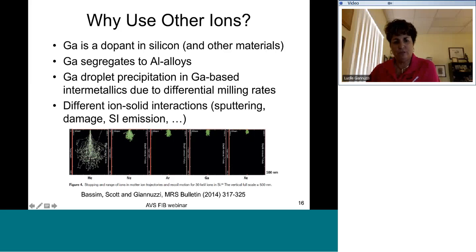Helium has a very small spread at the surface, but then travels microns length into a sample. Whereas these other ions that exhibit so-called sputtering and heavy ion effects will be stopped only a few tens of nanometers within the surface. So it really depends on what you want to do, how you want to do it, what effects you want to get for either sputtering or to minimize damage, etc., which we'll talk about.